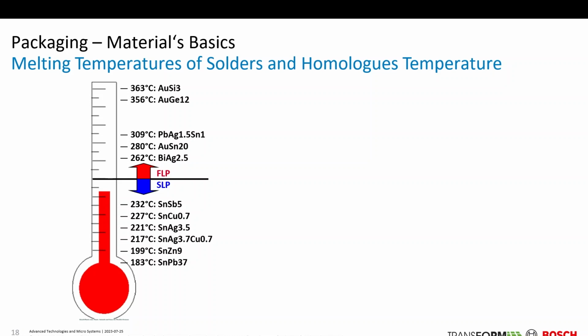The old world was tin-lead with this eutectic formulation, 183 degrees C for the eutectic one. But regarding regulations like RoHS, WEEE and ELV from the EU legislation, this is banned, in principle. For some disciplines you can still apply this solder alloy. You can apply tin-zinc, for example, but then you may have problems with corrosion issues. Then you have these lead-free base solutions.